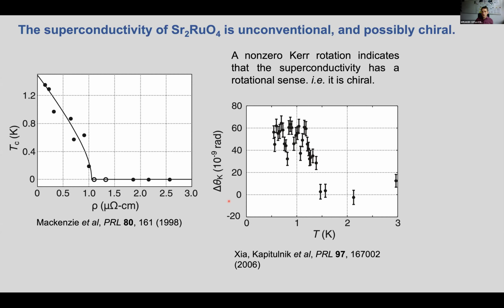It has, in addition, a Kerr rotation, a small but definite Kerr rotation of about 60 nanoradians at low temperature, and then as temperature is raised, this Kerr rotation disappears at Tc, and that indicates that the superconducting order parameter has a rotational sense. It is chiral.